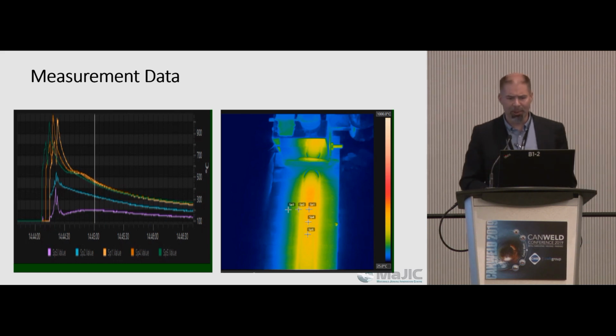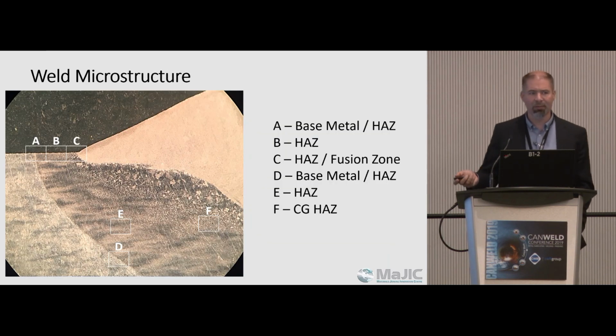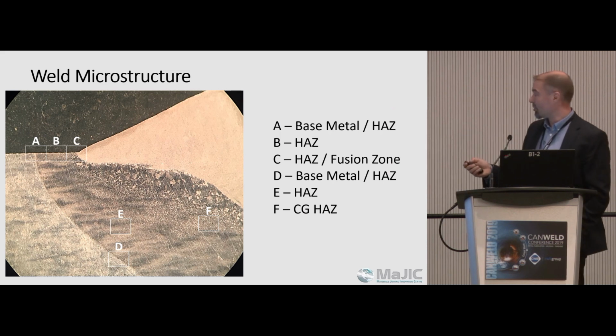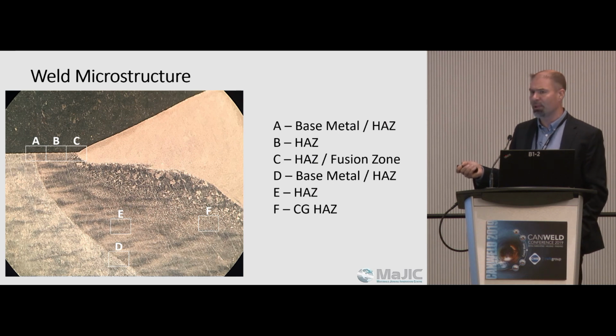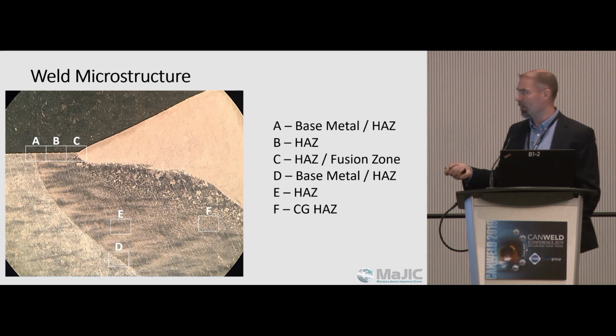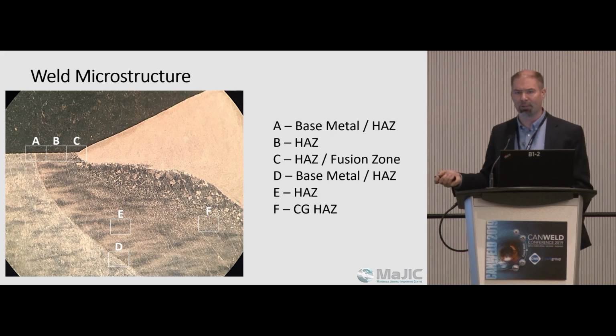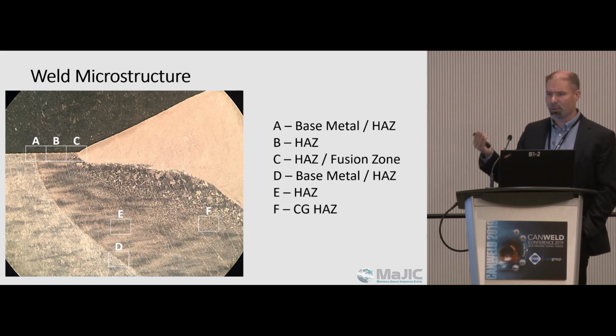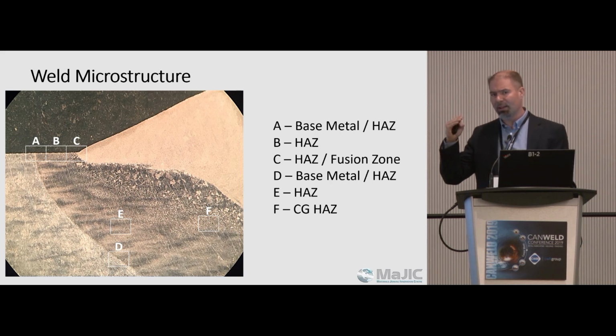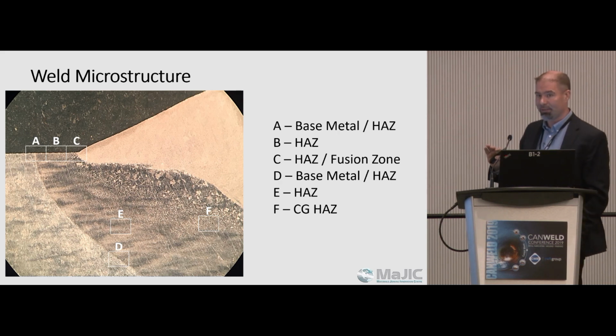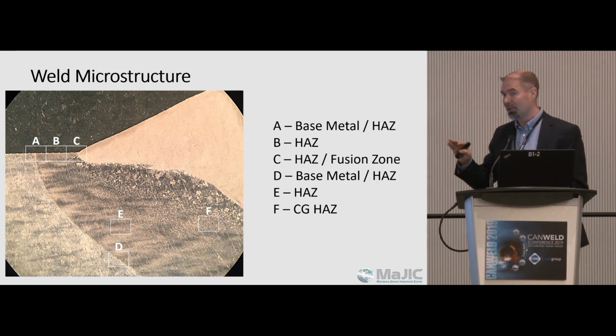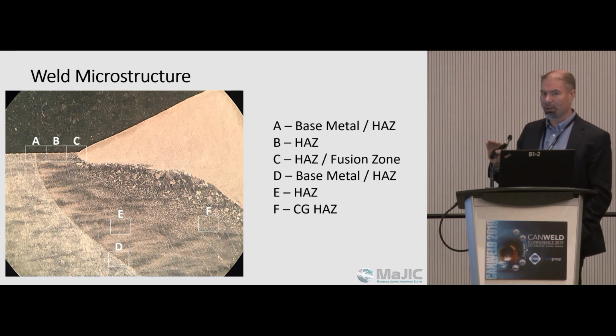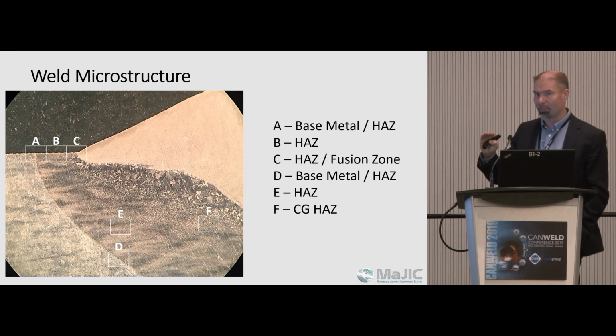So then we look at the weld microstructure. Six areas of interest up at the surface here, and there's a good reason for this: the surface temperature is really what we were looking at with the thermal camera. We're not able to see what's going on subsurface. The thermal camera is a visual thing. It's looking at the temperature of what you can see. So contrary to popular belief, thermal cameras don't see through walls, unless those walls are made out of thermally transparent material. So not all the movies are right.